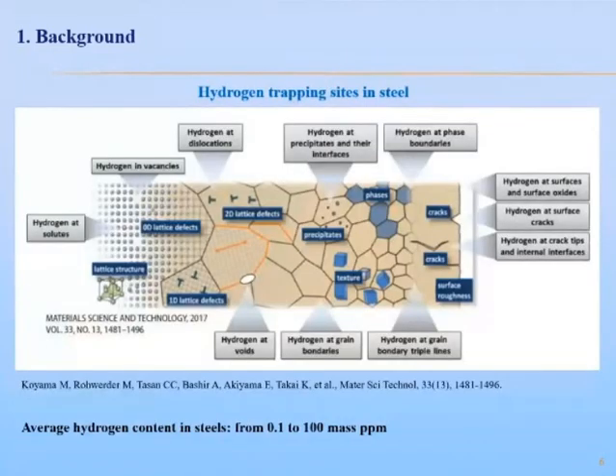Hydrogen can be trapped at various types of lattice defects in steels. Here you can see a nice illustration by Koyama and others showing different hydrogen trapping sites in steels, such as vacancies, certain solutes, grain boundaries, and phase interfaces, triple points, precipitates, and others. The main challenge in identifying the governing mechanism behind hydrogen embrittlement lies in mapping hydrogen trapping and kinetics with microstructural sensitivity.